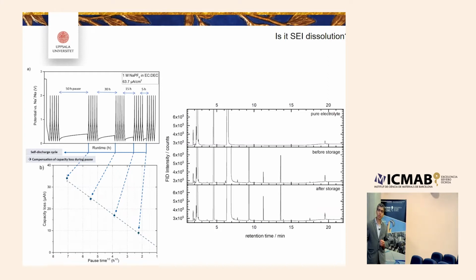But one thing interesting for us is that before and after storage, we do see differences. The intensity of these peaks is changing. These peaks here also are changing. There's a little bit of change here. So things are happening before and after storage. That's another confirmation that it's a dynamic system, with changes in the concentration of species inside the liquid electrolyte.